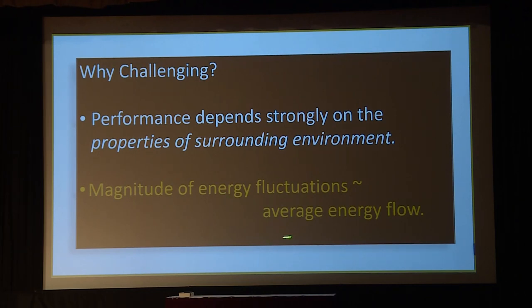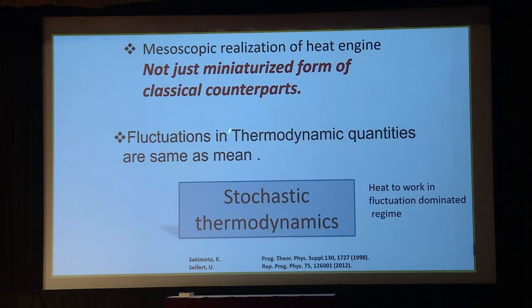And the fluctuations, when you have very small particles, are huge. You will not really work with the average quantities. Average is the same as the variance. This is the problem of small systems. So it is not mechanical miniaturization which is a challenge. The challenge is that you have to work with fluctuating thermodynamic quantities. How you calculate heat and work with those fluctuations is the whole paradigm of stochastic thermodynamics. It is thermodynamics with fluctuating quantities.